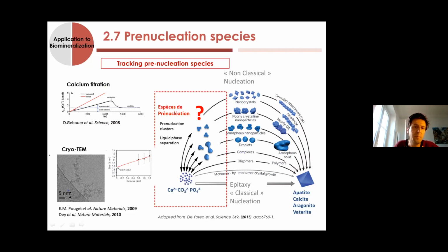In the first case, people saw that when adding calcium to a carbonate solution, only part of the calcium remains free in solution before nucleation, meaning the other part is already interacting with calcium but is not yet nucleated, it's still solute. With cryo-TEM experiments, people showed that these solutes are very small units of about 1 nanometer in diameter, but stable in equilibrium with the free ions.